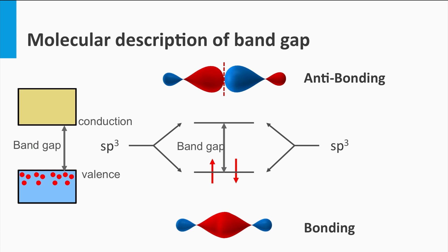If we look at the molecular orbital, its bonding and antibonding states are discrete energy levels. However, if we look at a solid like crystalline silicon, its network contains many silicon-silicon bonds. All these bonding states do not appear as one single discrete energy level, but instead spread their energy levels continuously over a broader electronic band, like the valence band or conduction band.